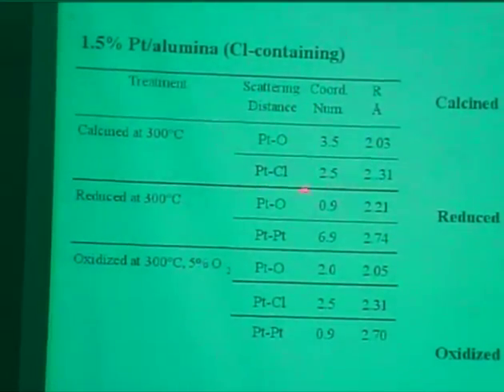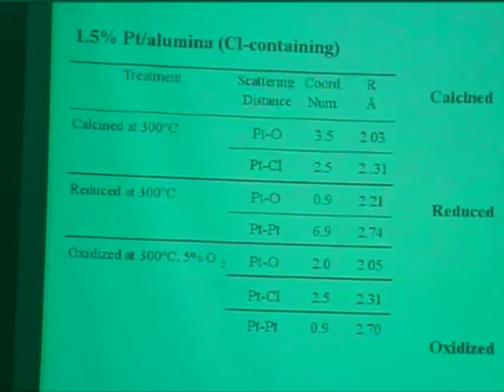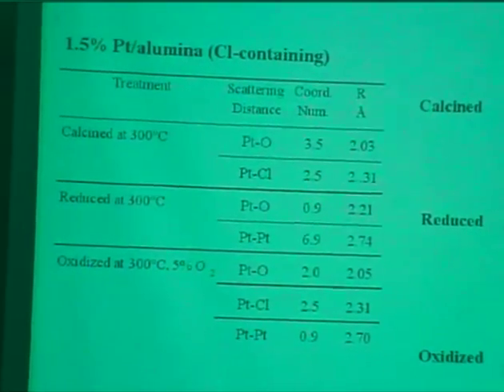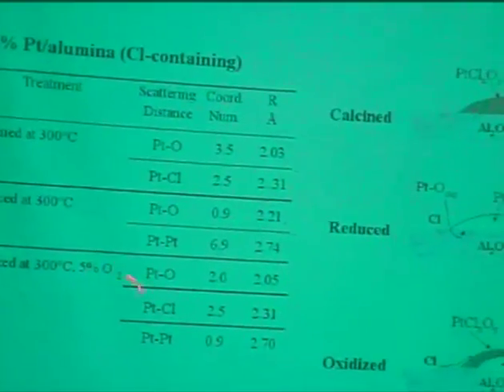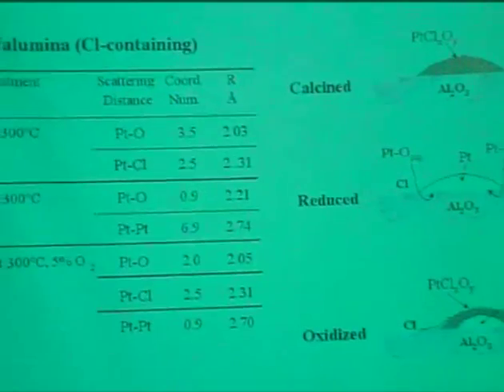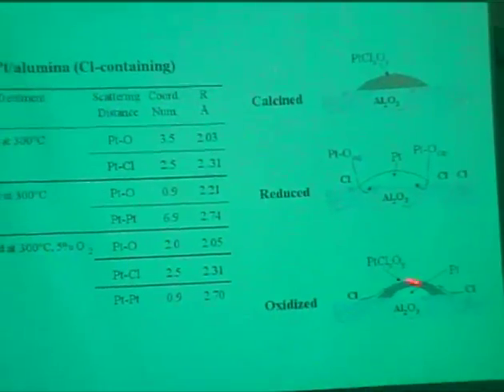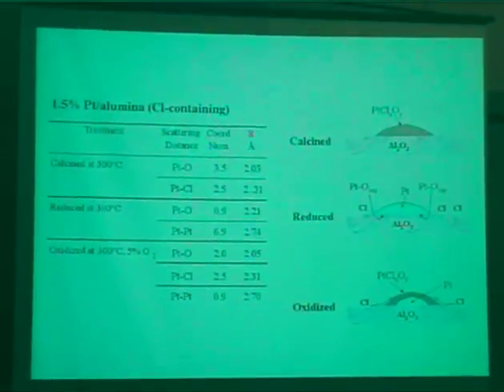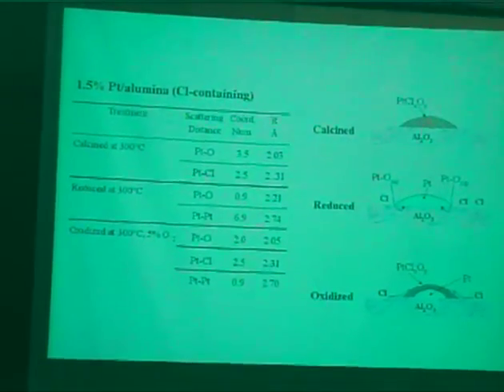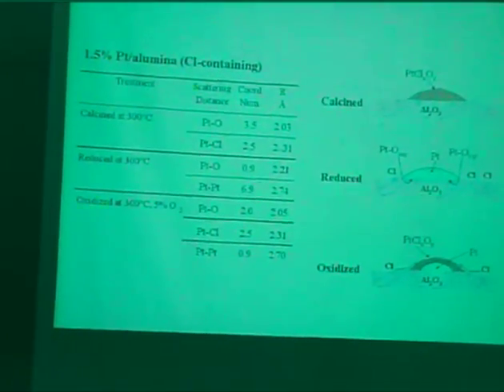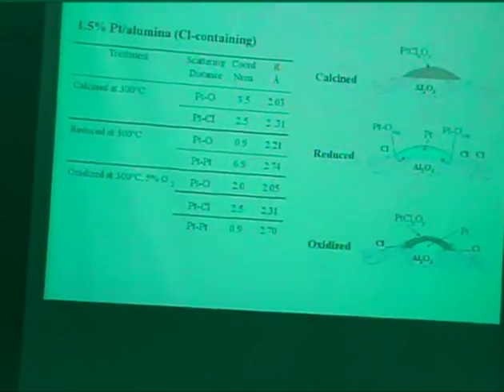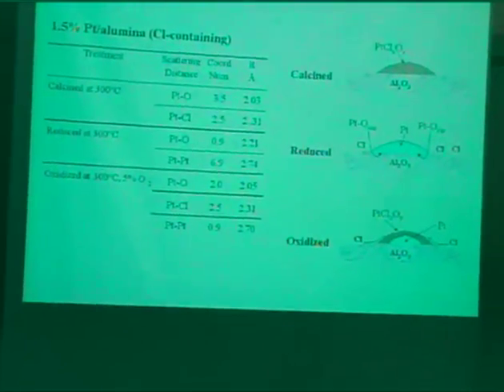Okay? And again, I insist it is possible to get rid of this if you do it for a long time and higher temperature. We use this milder treatment so that we don't have sintering. But if you do it for, as I say, 40 hours was the last result that we came out with, it's pretty difficult to get it out of the alumina, not so out of silica. Okay? So if you've done the preparation on silica, which I don't have,